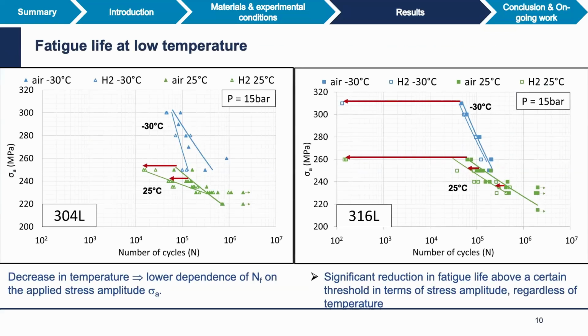Let me move now to the high cycle fatigue test results. Again, 304L on the left-hand side, 316L on the right-hand side. So here, basically, we compare the data obtained at room temperature and at low temperature, in that case, minus 30 degrees C. And so as expected, regardless of environment, we have a higher resistance at low temperature than at room temperature.